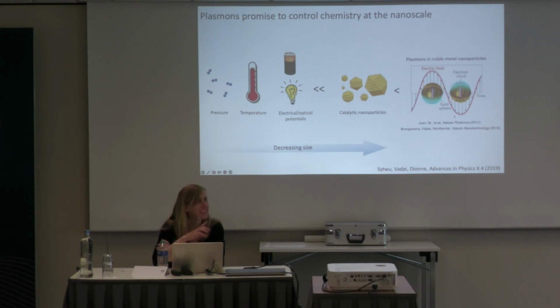So you know that light is an oscillating electric and magnetic field. If for the time being we just think about the electric field of light, when that interacts with a metallic nanoparticle, it causes the free conduction electrons to oscillate back and forth in response to that driving electric field. So you wind up getting this cloud of electrons that gets displaced, in this case up and down, to match the polarization of the electric field of light. For the small nanoparticles that we'll be dealing with in this presentation, we basically just have a dipolar-like resonance in our catalytic nanoparticles.